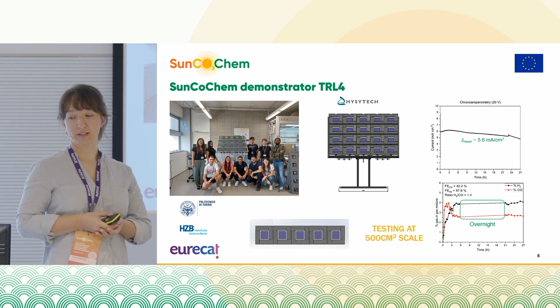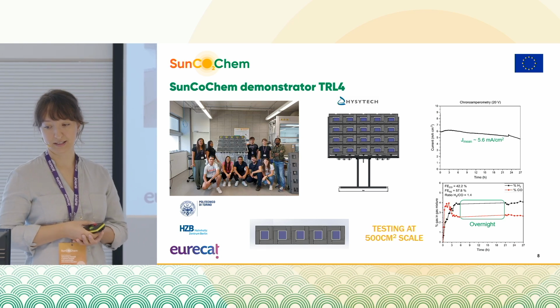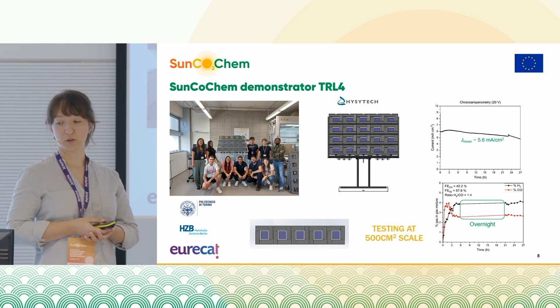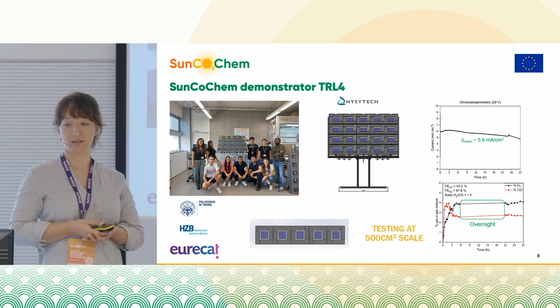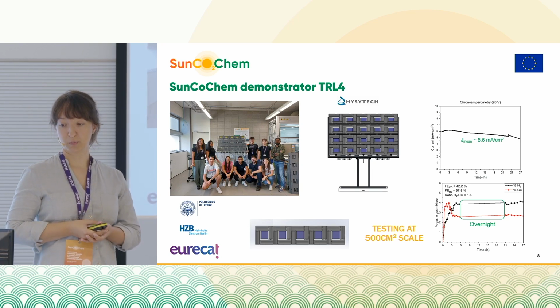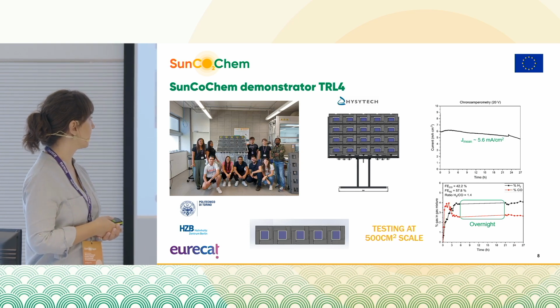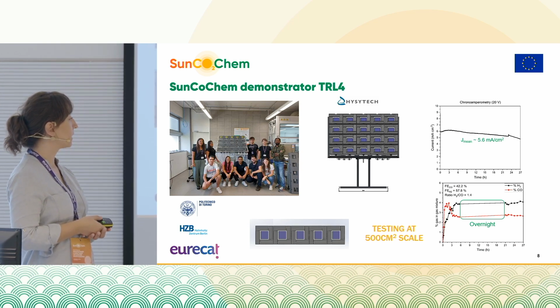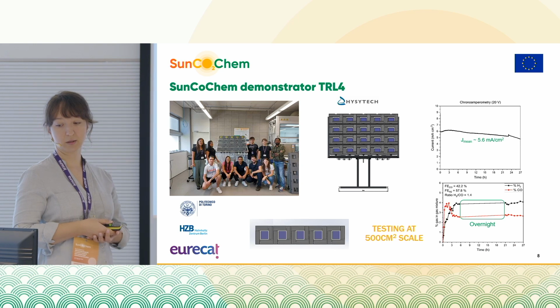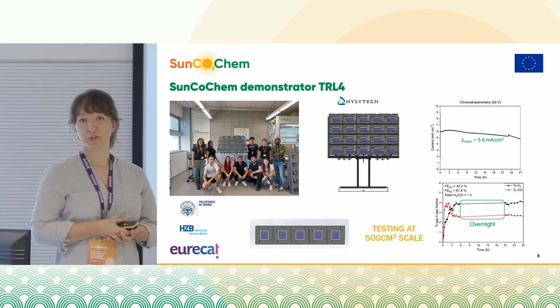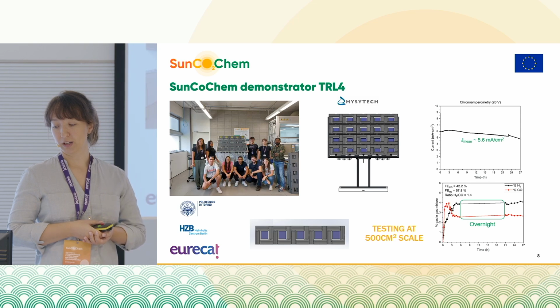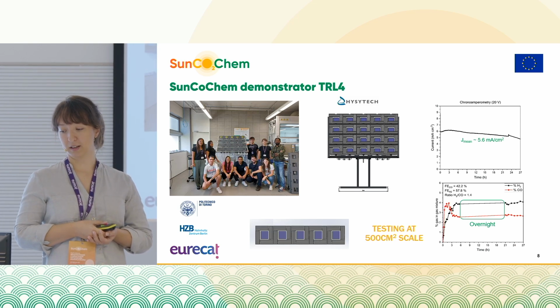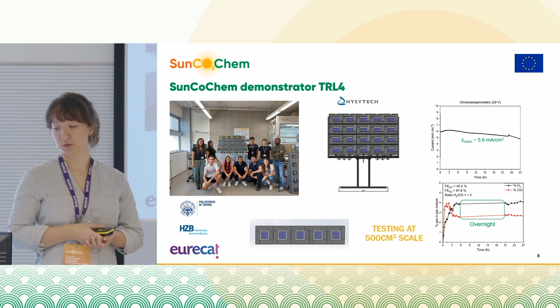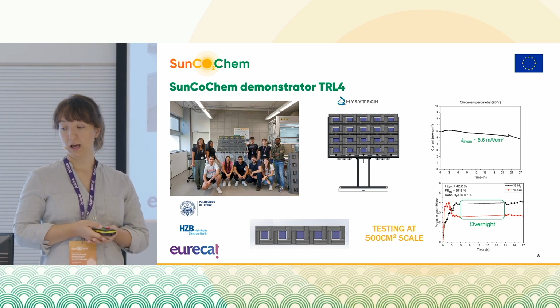Then from the single cell, we moved to the bigger scale. We had a reactor that was designed and constructed by Hysytech. It was installed in EURECAT premises and tested. First, I will show you the results that we obtained from testing of a single string, which was composed of 5 cells that sums up to 500 square centimeter of active area. After many months of experiments, we achieved a stable syngas production during 27 hours and also pretty stable current.